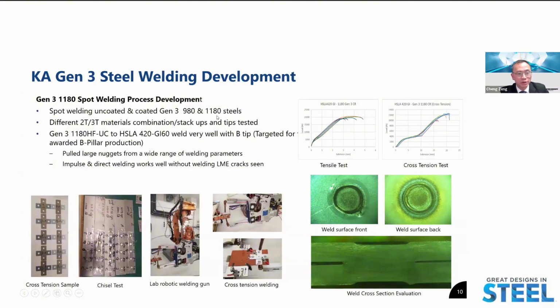One other concern is zinc coated steel, the welding LME concern. That's why we did a lot of study, following a similar methodology as shown here. We did the chisel test and coupon test under different parameters, and then the cross tension test, to find any welding LME in the interfacial. As long as you have cracking in the interfacial, then when you pull it will immediately crack, and you will see the curve is significantly different.